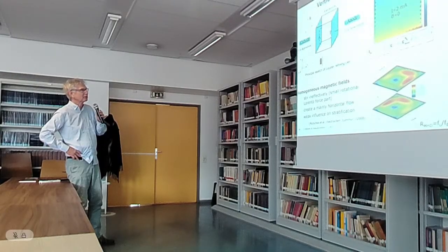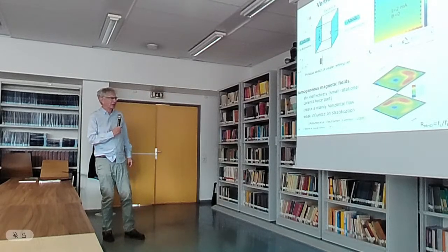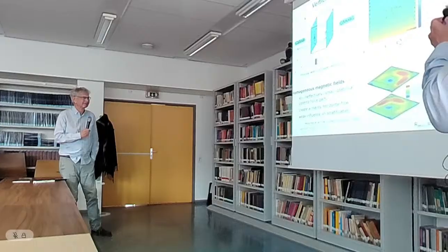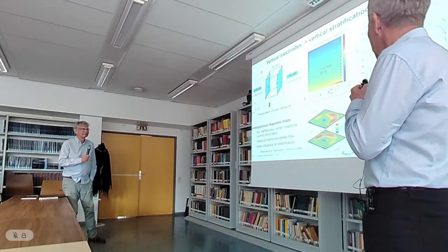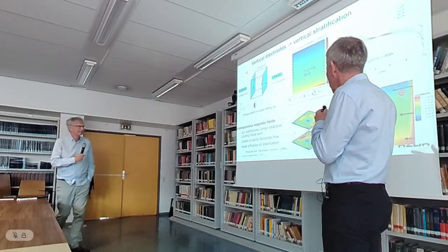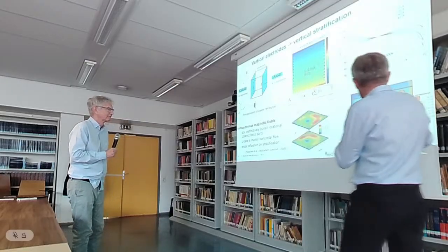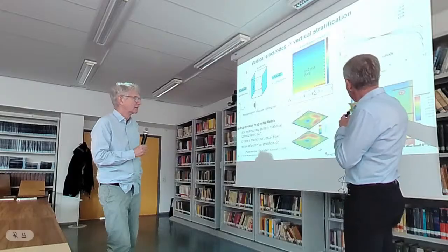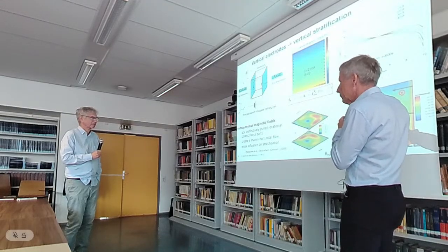Okay. Well, maybe here. So it's a magnetic field stirring effectively and creating mainly a horizontal flow. Yes. So how do you circumvent that effect? How do you make it more efficient? Yeah, what I wanted to say here is that when we started to investigate this, we started with applying homogeneous magnetic fields, and we found out that doesn't work very well. The best or the strongest effect that is being achieved in terms of enhancing the current, as an indicator, is indeed a vertical magnetic field. And there's a sketch here. You see how the boundary layers are evolving on both sides of the electrodes. And because of the different thickness, you have a different magnitude of the electrical current in these areas. And then you have the Lorentz force, right?